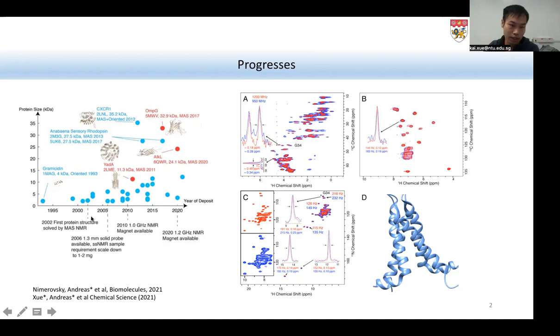One thing worth noticing here is that in the past 20 years, we have had an increase of approximately 200 megahertz every 10 years. And I hope this trend will continue, because we definitely benefit from higher magnets. And here I show a comparison of the spectra obtained at 1.2 gigahertz and 950 megahertz fields. The sample that we use is M2 membrane protein. As you can see, we gain in resolution not only in ppm value but also in absolute hertz values. So our lines actually get sharper.